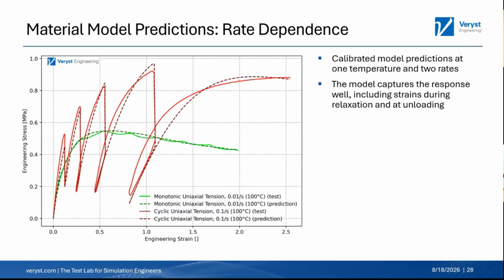So what does that mean in practice? Here's a material model I calibrated to that data. The solid lines are the tests. The dashed lines are material model predictions. And you can see we've got a very good prediction between those two. We're capturing the stress strain response very well. We're capturing the unloading well. We could do a little bit better in capturing the hysteresis.